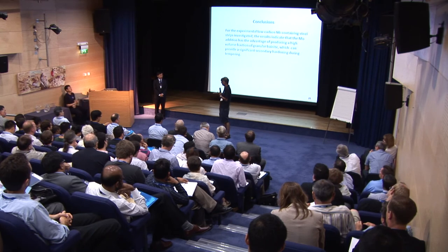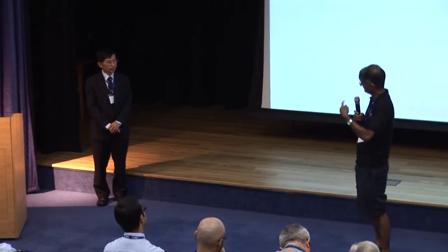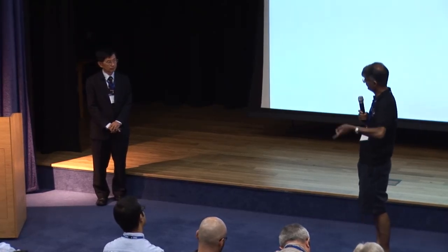Excellent lecture. Thank you. What is remarkable is the stability of the structure. Even with tempering at 600, you maintain the strength and the dislocation density, and increase ductility. So the idea would be that the 600 degrees C happens during coiling. Yes, exactly.